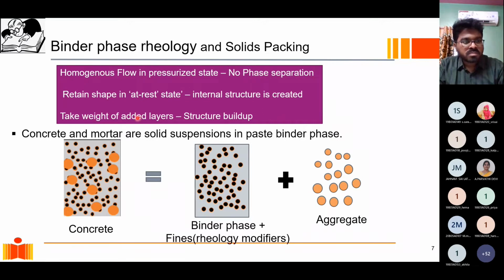Then once it comes out, that means once I remove the pressure, once it has come out of the nozzle, it is in the at rest state, that means now it is sitting at rest, an internal structure has to be created inside the material so that it keeps its shape. Now, not just that, once I finish depositing one layer, when I start depositing the second layer, the first layer should be strong enough, should have internal structure that it should be able to take the weight of additional layers. And we call that structure buildup. There has to be a buildup that has to take place.